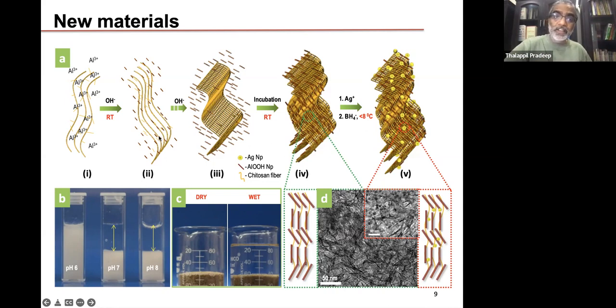This entire material, although is made in water at room temperature, they finally become a sand-like composite over which you can keep water for years together. This entire process is very similar to biological synthesis. Just as seashells are made in water using calcium carbonate or calcium ions, carbonate ions and others over a biopolymer template, over a long period, this similar process, you can do it over a few hours. And that's the whole idea of creating such materials.